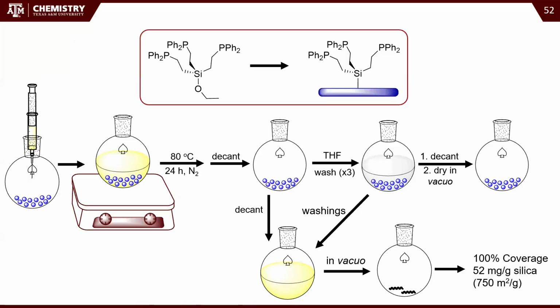So immobilizing these ligands is pretty straightforward. We just take our ligand in a toluene solution and add it to well-dried silica. If you dry the silica well enough, there's really only surface silanols. Those silanols will cleave that off. You'll hydrolyze that off and get ethanol, and then you'll have a silanol. And then that silanol will condense with the silanols on the surface. If we do that and then wash off anything that's not bound, we get about 52 milligrams per gram coverage, which is not so good.